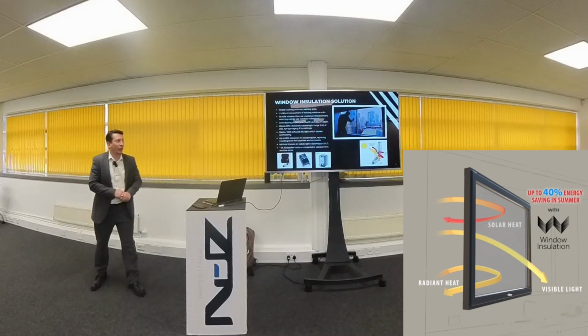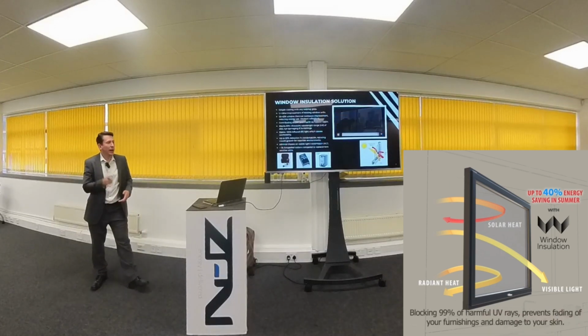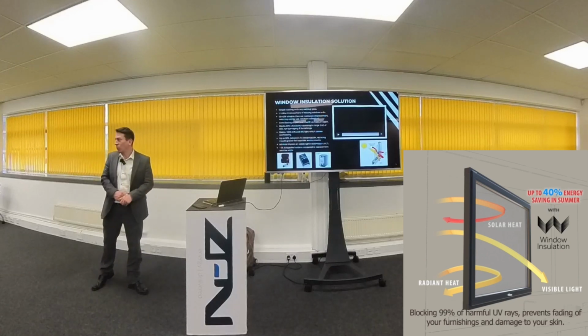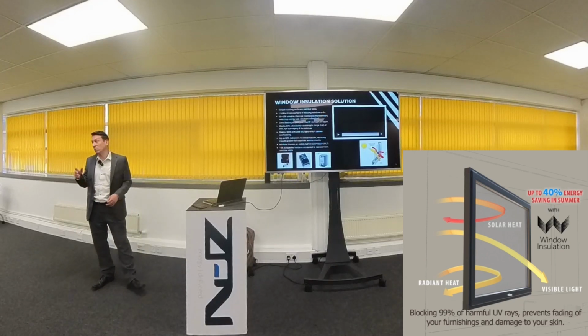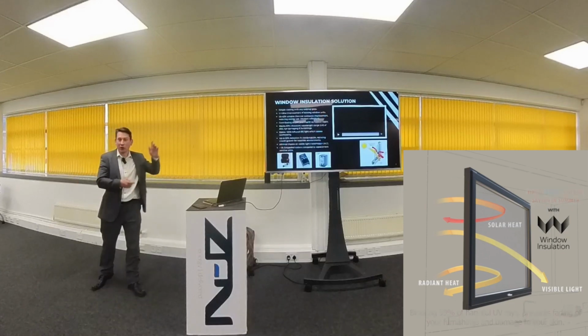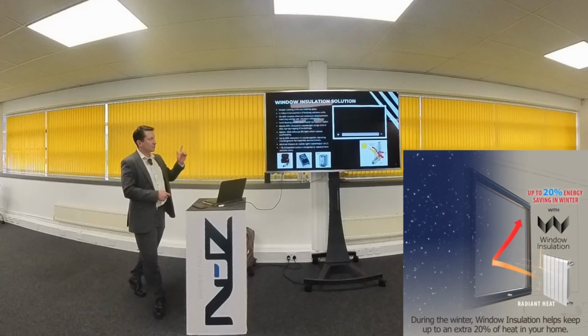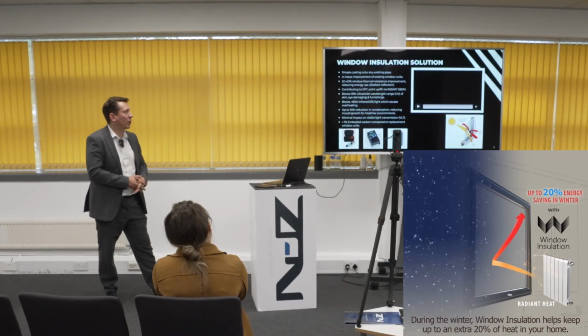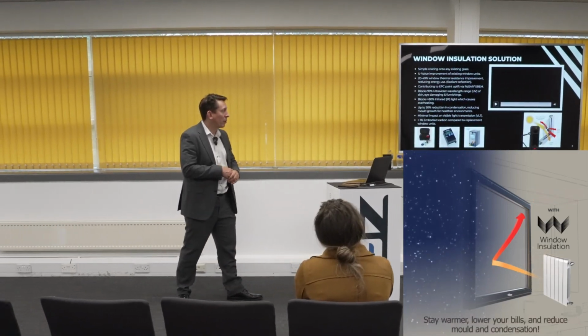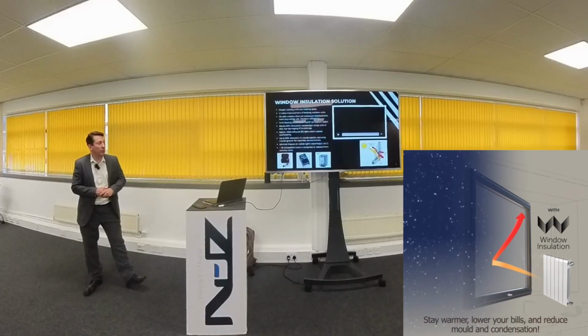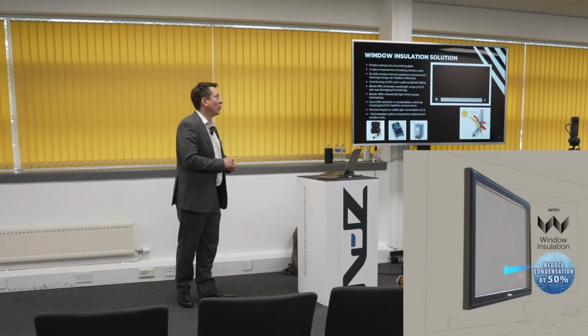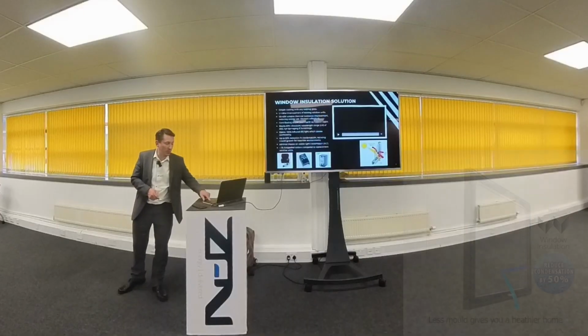Blocks over 80% of infrared, that causes the overheating. And again, if I use 4mm glass as an example, it cuts around about 15 to 20% of IR. Put the coating on, it's over 80. Up to 50% reduction in condensation, which reduces mould growth on the glass. Minimal change in visible light, and it's less than 1% embodied carbon compared to replacement.